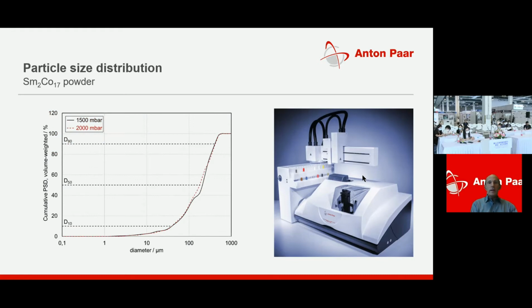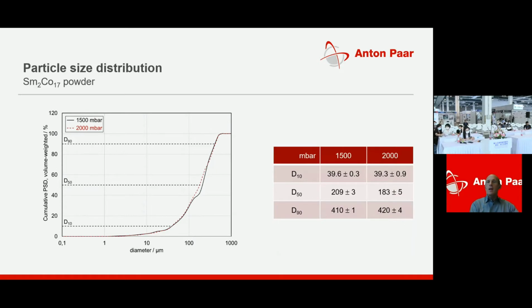When we now look at the cumulative particle size distribution curves for powder aerosols generated by either 1,500 or 2,000 millibar of pressure, and when we extract the characteristic descriptors of these size distributions, we find only marginal differences in the D10, D50, and D90 threshold values. We conclude that the higher pressure, which we applied for getting a better dispersion of the powder sample, did at least not destroy any of the individual particles.